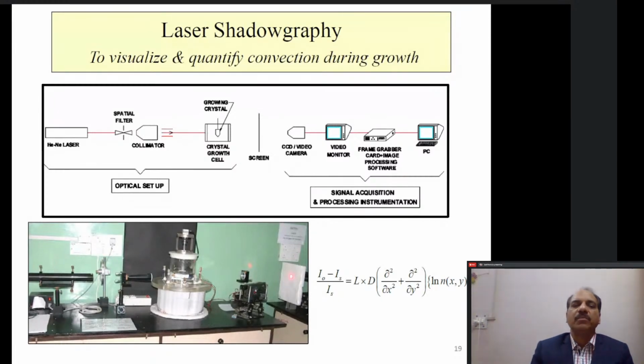So we set up this optical technique, which is nothing but a small laser. We use a helium neon laser of low power, something like 5 to 10 milliwatt. Then we have a spatial filter. The spatial filter is nothing but a beam expander, a collimator and a pinhole arrangement, which basically removes the defects in the beam. It makes the beam very smooth, right? And then this parallel beam of light is made to pass through a chamber. Now these chambers are specially designed. I'll show you the photograph of the chambers.